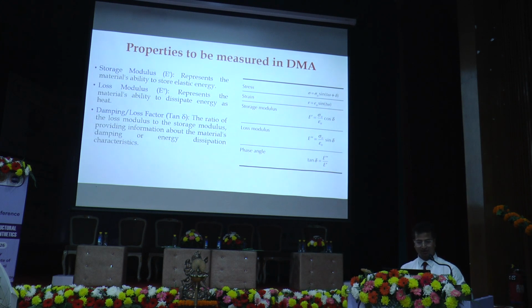These are the 3 main properties measured in DMA. Storage modulus, which is the material's ability to store elastic energy. Loss modulus, the material's ability to dissipate energy as heat. And damping factor, which is the ratio of loss modulus to storage modulus. So this was the working methodology.